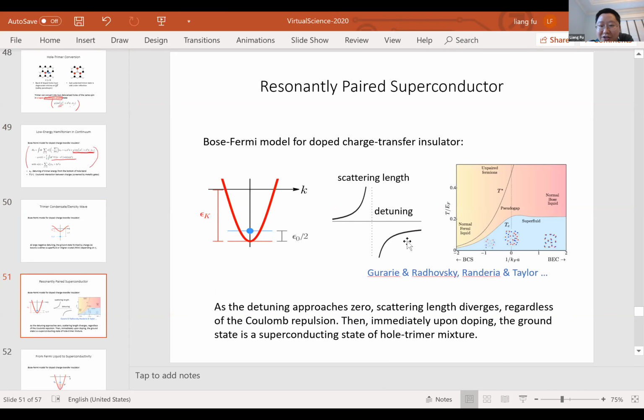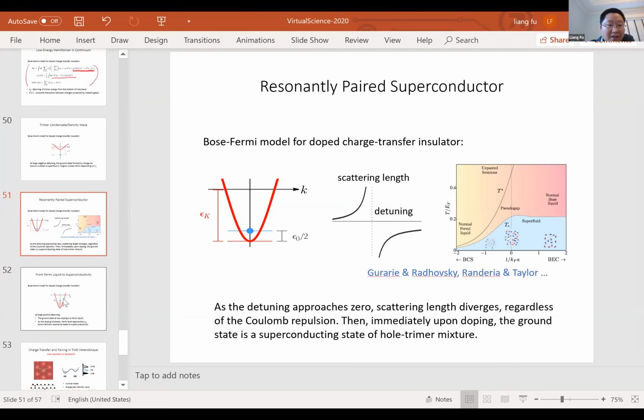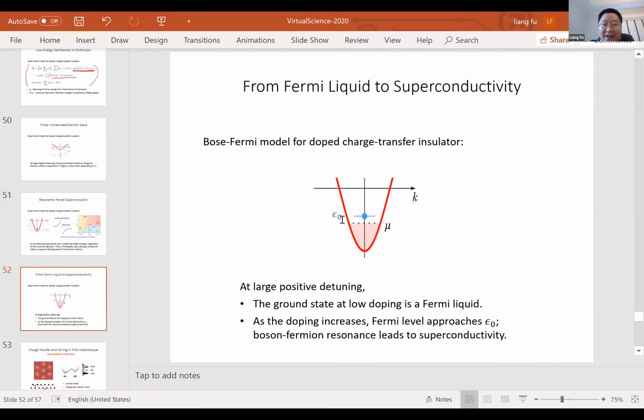So this resonant interaction between the holes and trimers leads to a superconducting ground state. Finally, if detuning is large and positive, then the band bottom of holes is below the trimer energy. In this case, as you start to dope the system, you first form some Fermi liquid states, and as the doping increases, the Fermi level approaches this trimer resonance, and then this resonance process again leads to superconductivity.